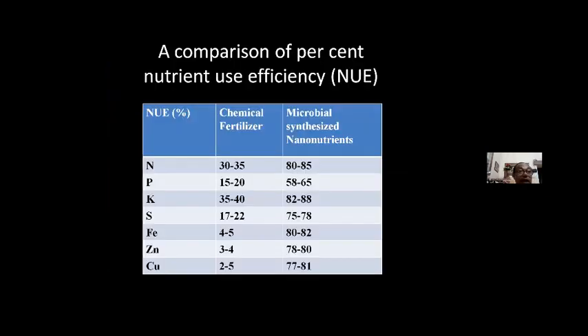And if you compare the nutrient use efficiency, you can see it here. The nitrogen use efficiency is increased. Chemical fertilizer, 30 to 35% only use efficiency, but biosynthesized nanoparticle 80 to 85% you find. Phosphorus 4 times increase, 15 to 20, which is increased to 60 to 65%. Potassium again almost 3 times, from 35 to 40% to 82 to 88%. Sulfur 4 times improvement. Micronutrient use efficiency is not more than 5% in any soil. This we are getting more than 80%. So almost 20 times use efficiency in micronutrient you can expect when you apply micronutrient as nano.